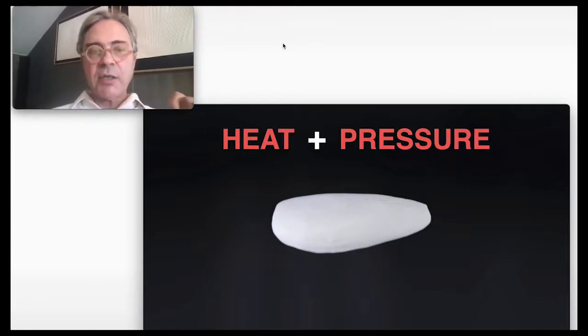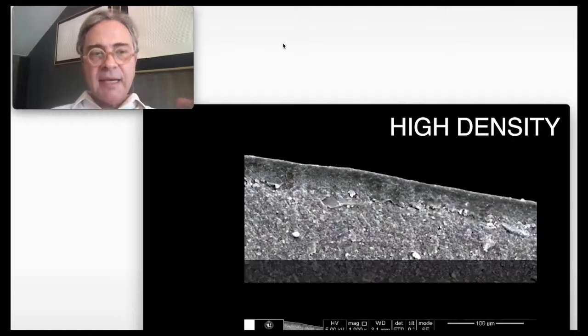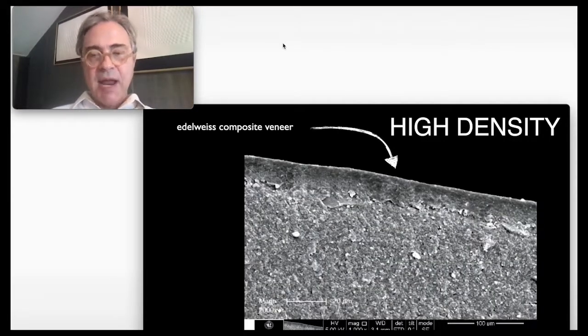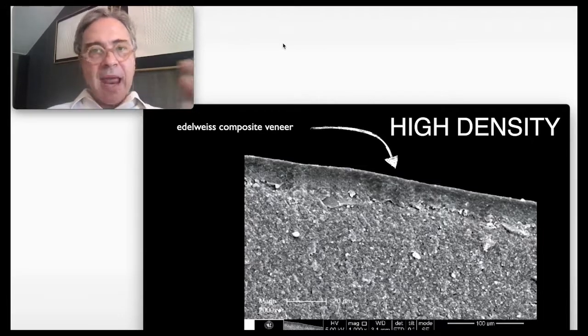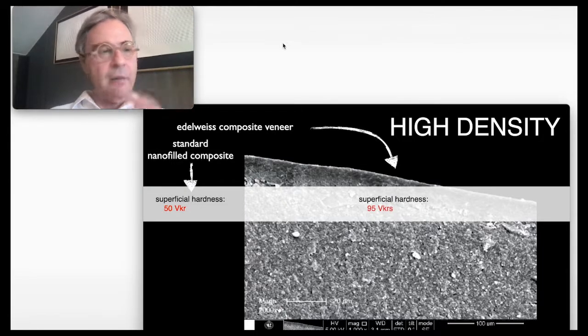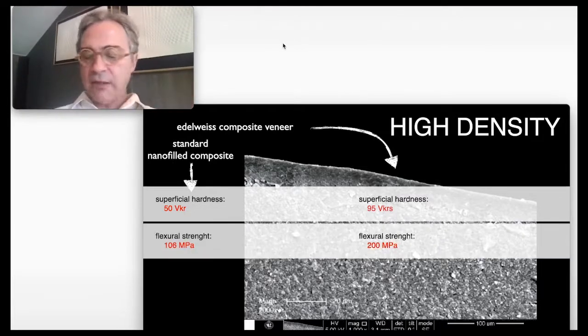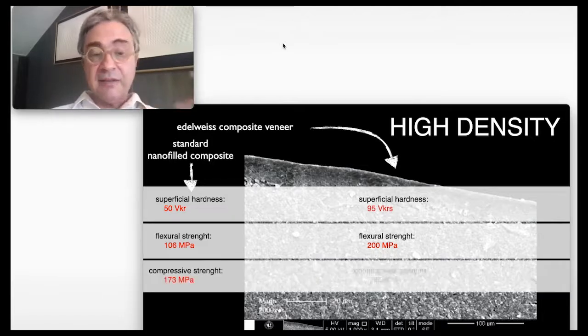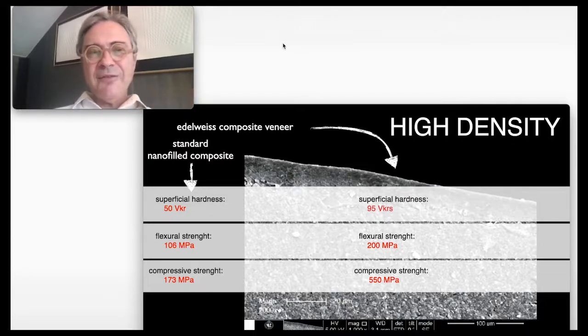And the addition of pressure increases density, condenses the filler particles, and eliminates the resin. So because of the low resin content and the high filler density, all the mechanical properties are remarkably improved compared to conventional composite restoration. So superficial hardness is twice the superficial hardness of a conventional composite, and flexural strength is twice the flexural strength, and compressive strength is almost 3 times the compressive strength of a conventional composite. So this is a very strong composite restoration. It's much stronger than a conventional composite, especially direct composite.